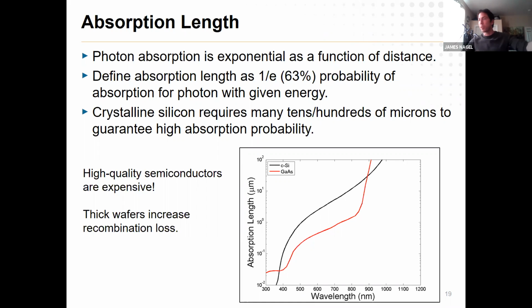Just for kicks and giggles, we're comparing something like gallium arsenide, which is a popular material for photovoltaics, and crystalline silicon. Gallium arsenide is a direct band gap semiconductor, which means as you get really close to the band gap, you have very short absorption lengths, and then all of a sudden it shoots off to infinity. As the photons cross that boundary, they basically stop absorbing. Whereas crystalline silicon has a much, much smoother curve. Looking at the graph, an 800 nanometer photon in gallium arsenide has an absorption length of about 1 micron, and this is a logarithmic scale. Compare that to silicon, and it shoots up to almost 10 microns.